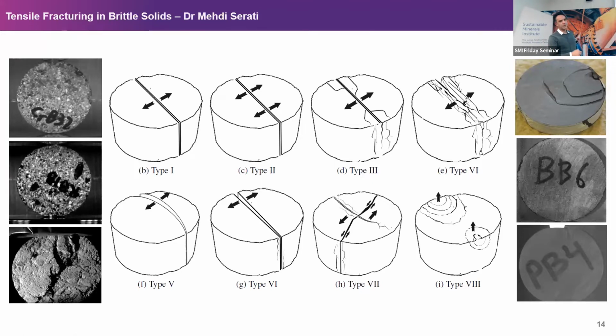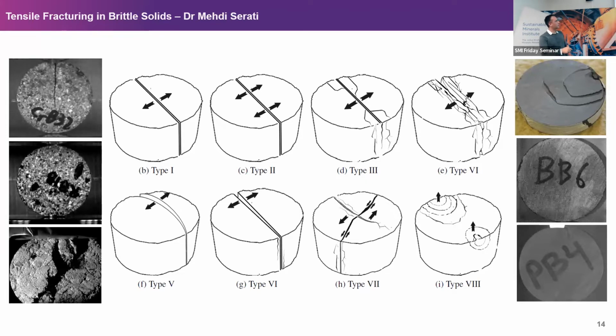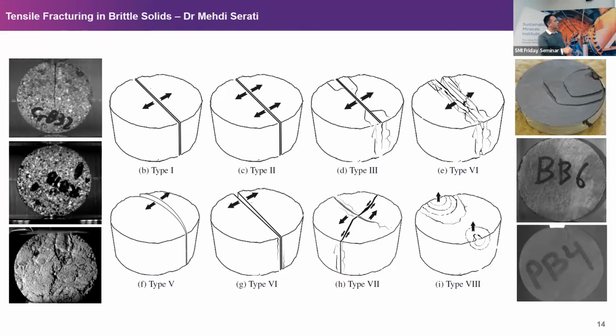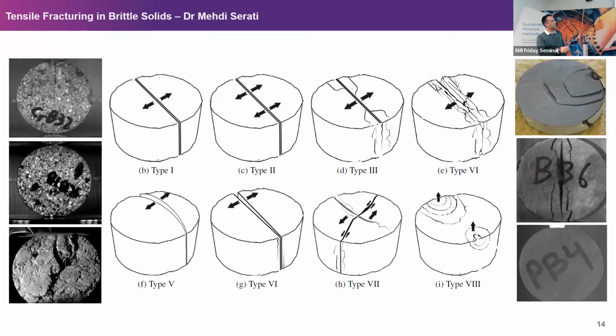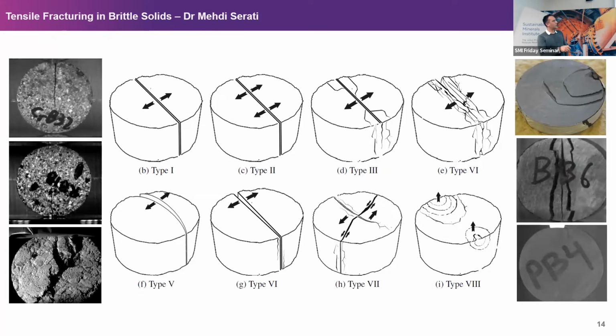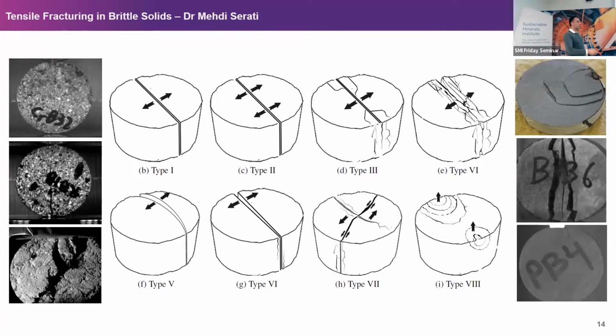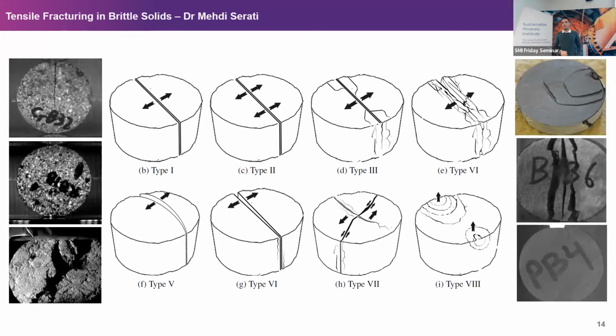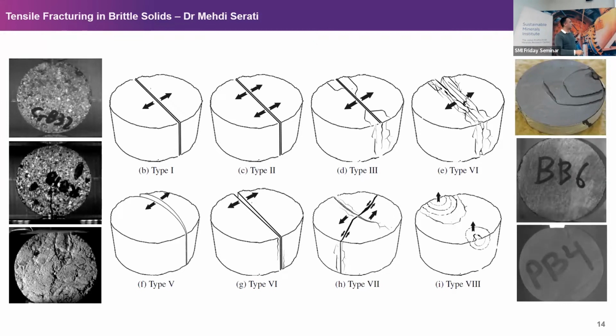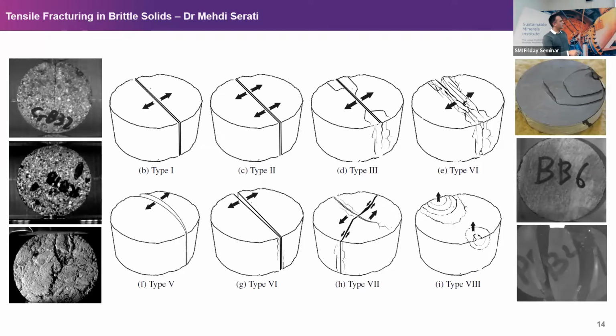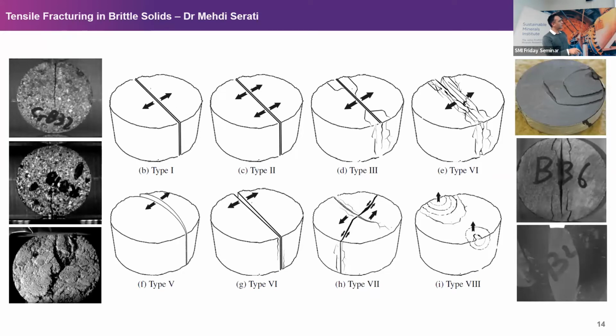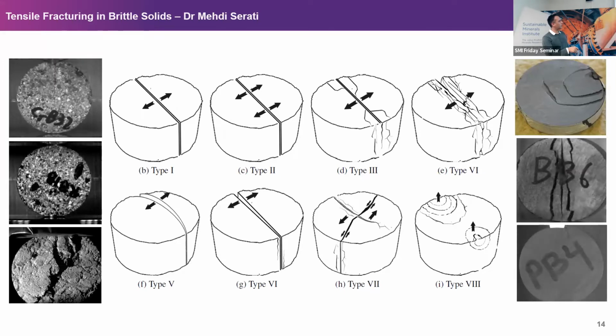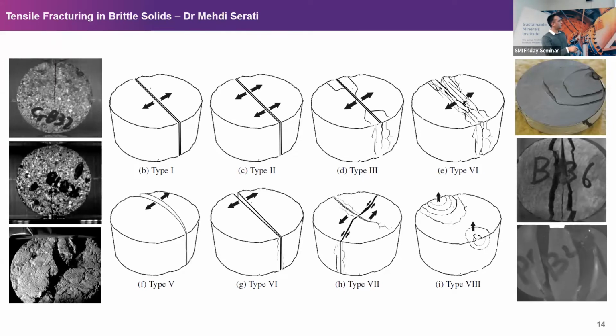Types 1 and 2 are very similar, and this is what you expect from a standard Brazilian test: you get a single tensile crack that splits the sample into 2 halves, and it initiates from the center. Type 3 is when you have some moderate-size shear fracture or conical-shaped fracture at the contact area when the tensile crack is fully propagated. Type 4, which is very violent, is when you have multiple cracking. Then we have types 5 and 6, when the crack doesn't start from the center, but rather starts in a straight, concave or convex shape from one of the 2 contact areas.